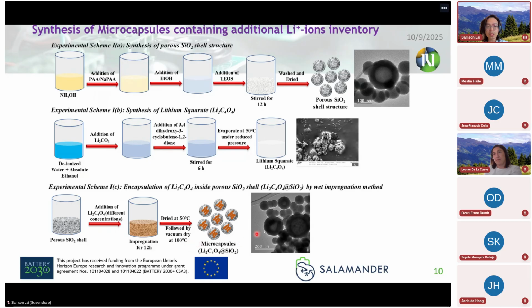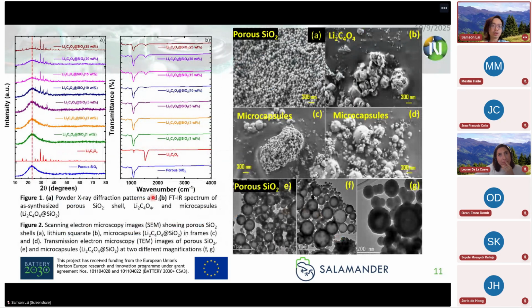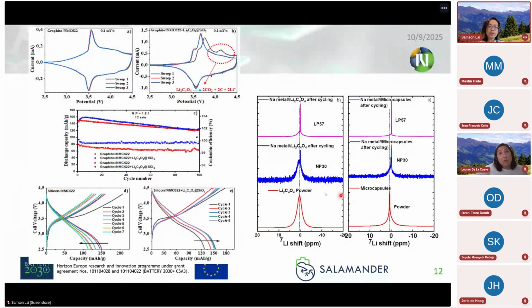So this shows that through XRD and FTIR that we can actually tune the amount of lithium squarate that we load, and it's quite corresponding to our synthesis conditions. And then you can actually see sort of at the TEM level, sort of these microcapsules and loading with the lithium squarate inside of them. And then when you do the electrochemistry, you can get a nice confirmation. Here with a standard cell, full cell graphite NMC622, and then here with the lithium squarate, you can see the decomposition is about 4.2, 4.3 volts, and lithium squarate decomposes to carbon dioxide, carbon, and lithium ions.